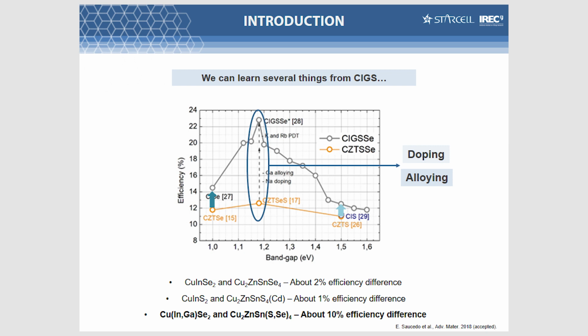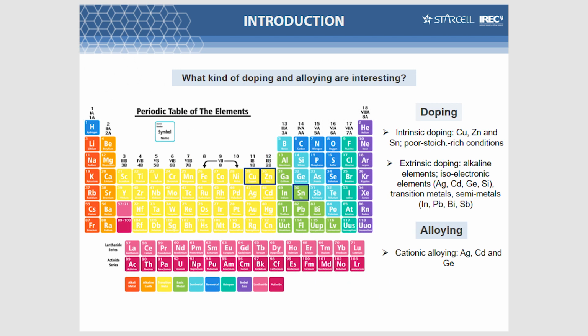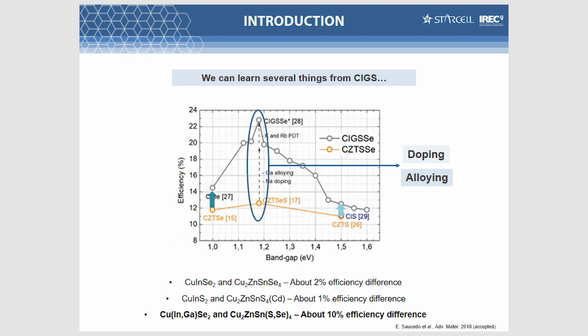For really jumping from this level of efficiency to this level of efficiency, CIGS has introduced two different strategies. Mainly alkaline doping and also gallium doping, gallium alloying, sorry. This means that CIGS, for pushing the efficiency from around 12–14% up to 20%, introduced these two types of strategies, doping and alloying. So this highlights the importance of studying this type of processes on kesterite.